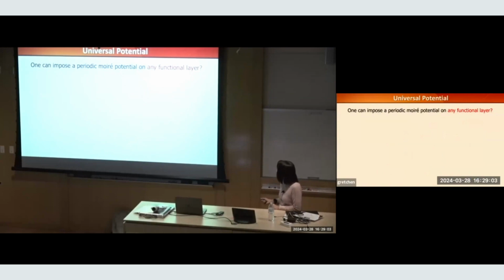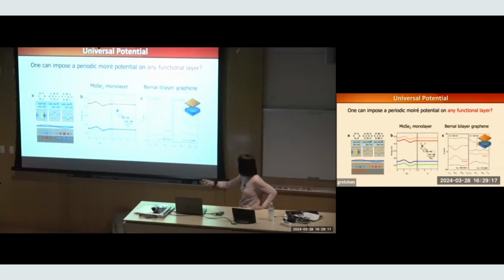I want to convince you I can actually do something useful with it. So of course I started by looking for a way to impose a Moiré potential on a functional layer. What I mean by that is I'm going to take my hBN, and then I'm going to have a functional layer, semiconductor or graphene, bilayer graphene. The electrostatic potential, just like the Coulomb potential between the atoms, will modify the band structure. So now I have a way to impose a Moiré potential on any functional material I put on the top, right? So this is universal in the sense the potential depth and the period are decided by the hBN. Whatever layer I put on top would experience the same potential, right?